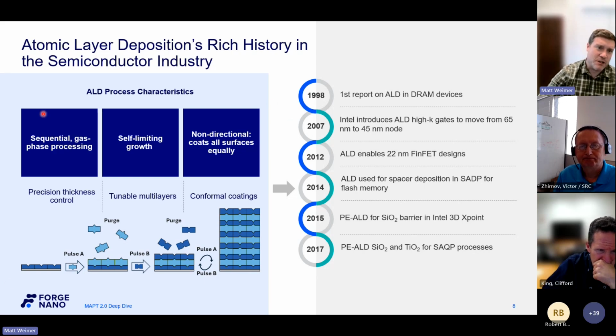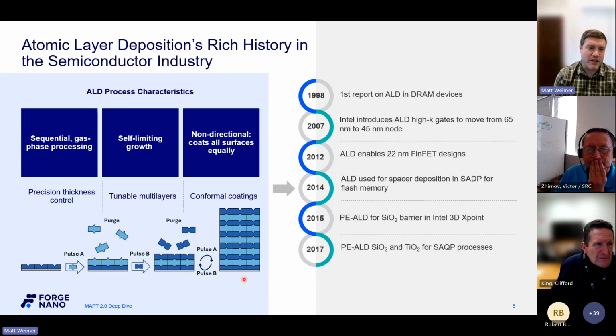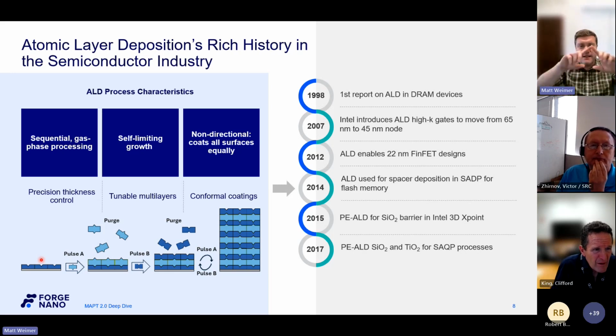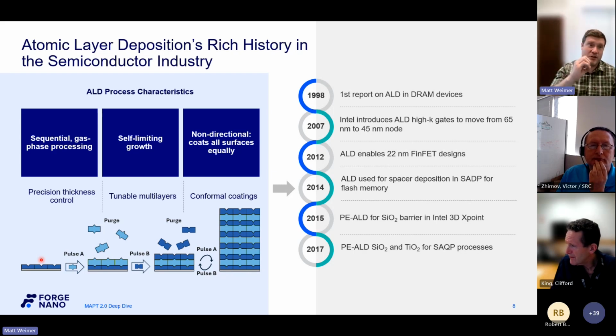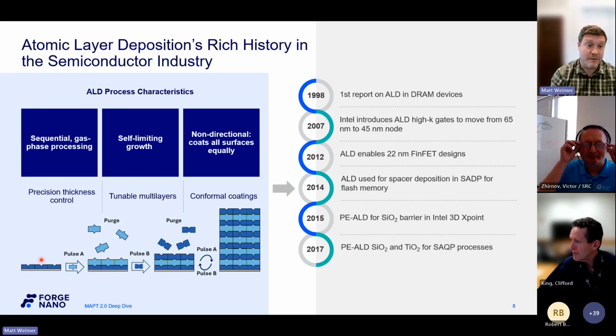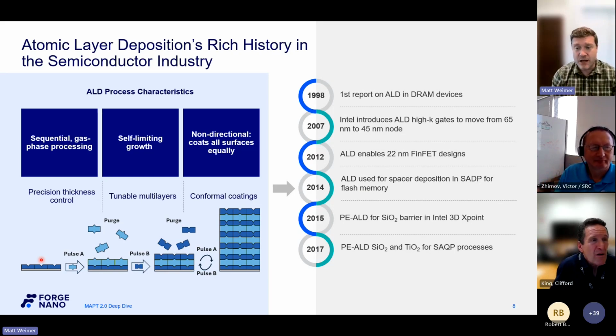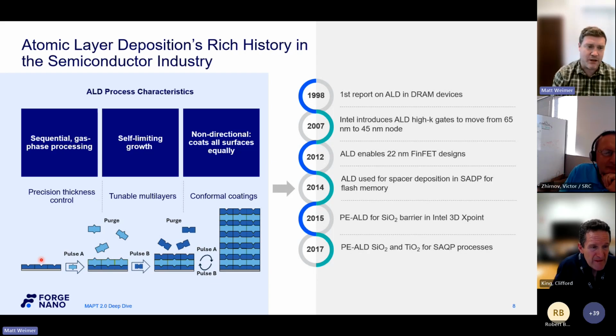So now if we switch back to the left-hand side here, I'll talk about this little schematic that we love to show in the ALD world, just on how it works. Now remember, ALD is a vapor phase technique, right? So it's really in the same class as chemical vapor deposition, but it's specialized. If you imagine it as a Venn diagram, CVD is this giant circle, ALD is a smaller circle inside of that. So another way to think about that is all ALD is CVD, but not all CVD is ALD. So what makes that differentiation? Well, it's the surface chemistry. It's self-limiting surface chemistry, to be specific. With CVD, it's not self-limiting. There are a few different mechanisms there we don't really want to go into.